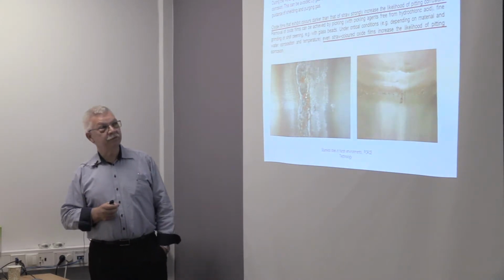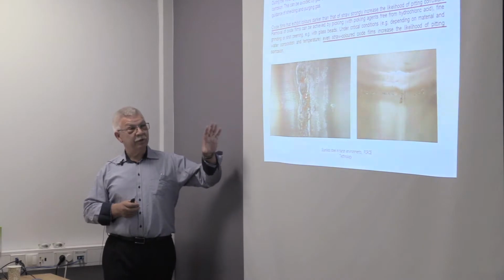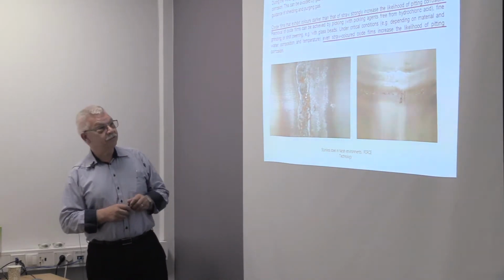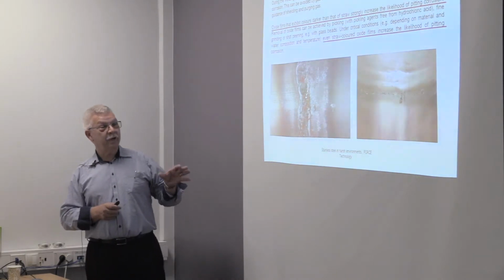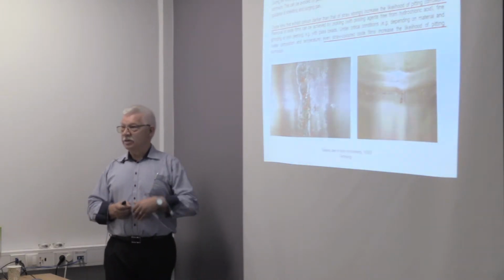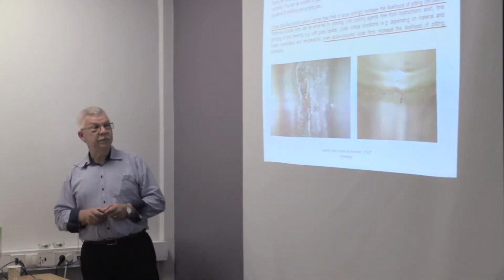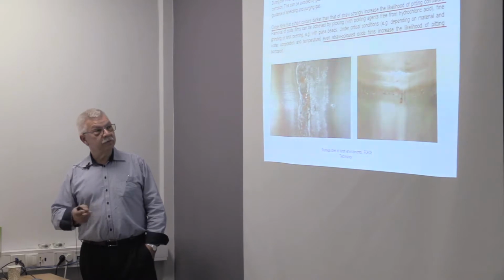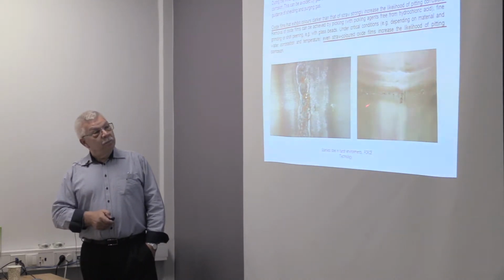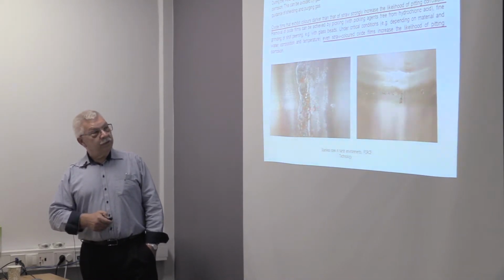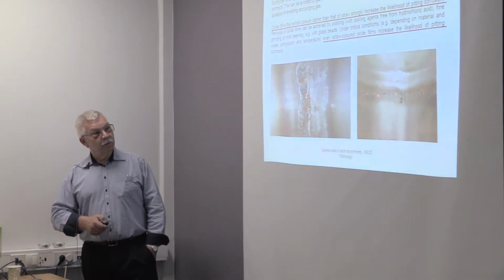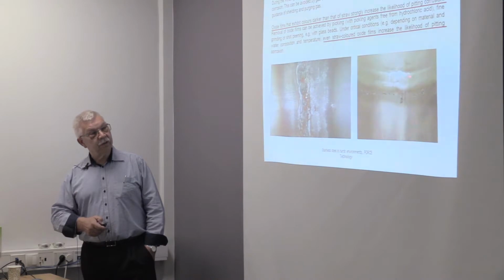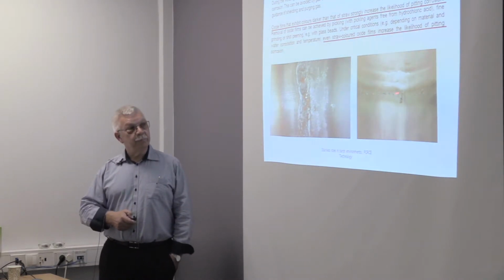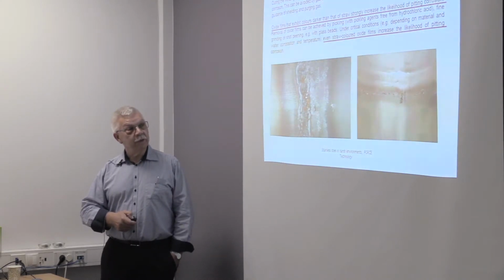So you need some references for that. I've not brought that today because I usually talk a lot about these reference charts, but they are available where you can select a certain degree of heat tint, specify that, and have it for inspection and acceptance criteria. But here you can see that a better purging than this will still give corrosion problems. The weld is perfect, but we still have pitting corrosion in this oxidized, colored zone from the weld heat.